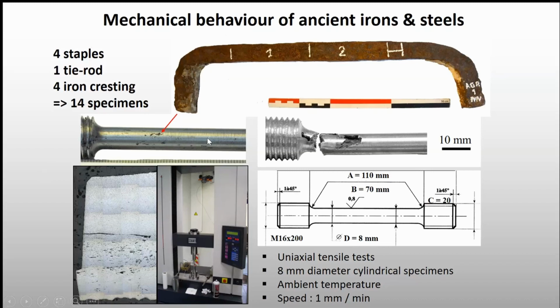So with these typical specimens, which were made inside each artifact, we tried to do 2 per artifact, but actually some of them broke before being tested, because you can see that there are many slag inclusions, we can see them here, and when there are big ones, it can really endanger the structure. So when we machined the specimen, some of them actually broke.